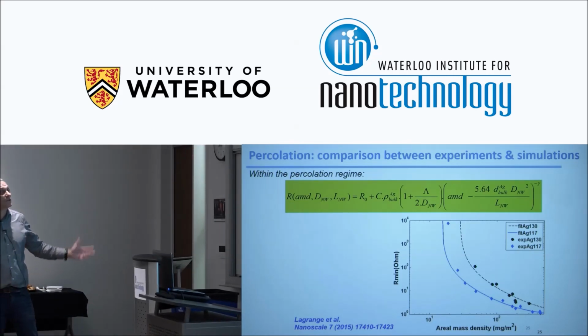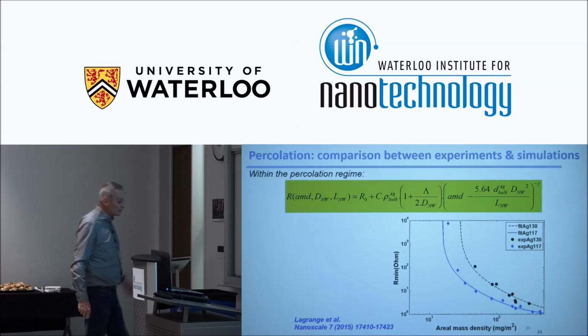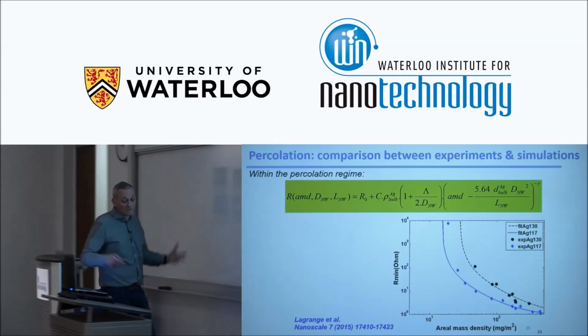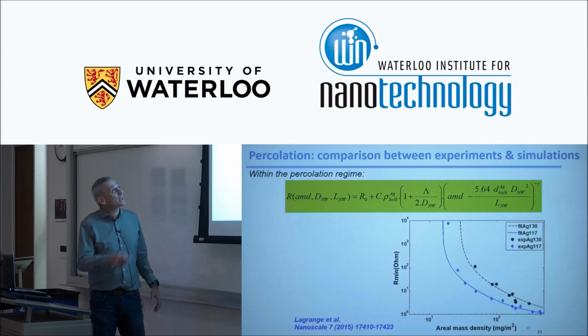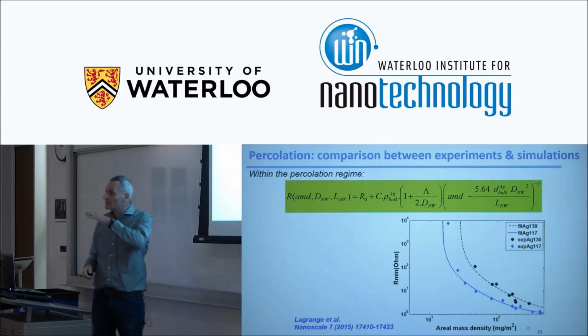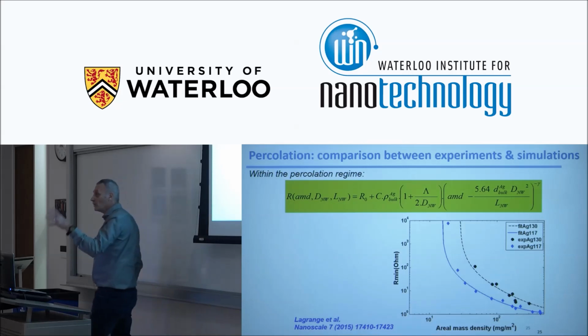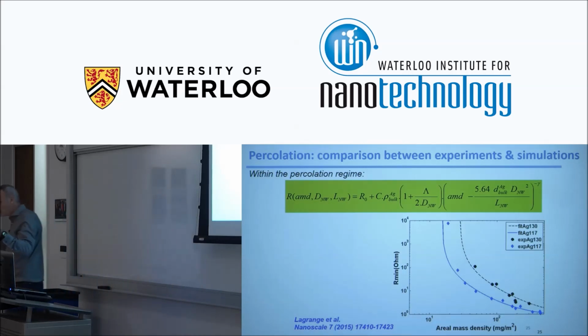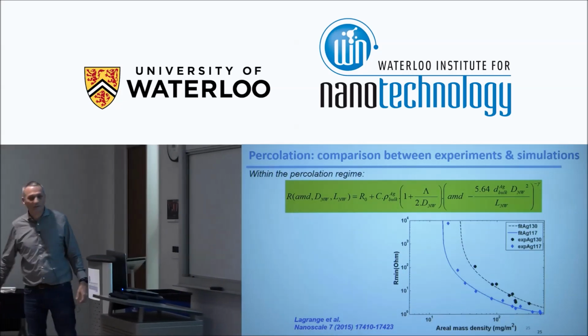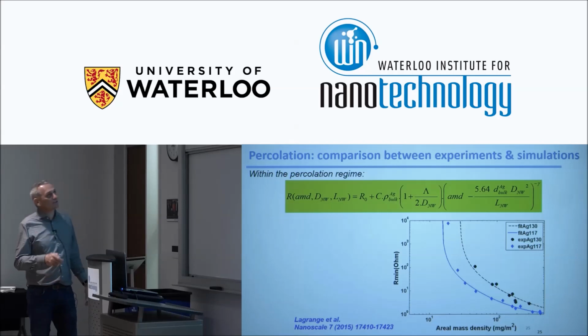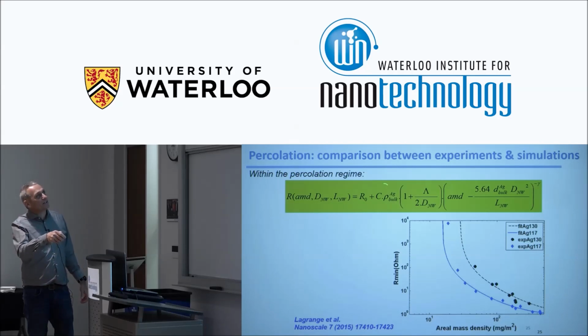So C, I'm not able to calculate it. It depends on the specimen size, for example, and there might be some other parameters. I'm not able to calculate it, so it will be the only fitting parameter, because this one we can measure. If we deposit a thick silver layer, for example, we can say that the resistance is so small that we are going only to measure experimentally the instrumental series resistance. So we know this. C, we don't know, that's the fitting parameter, with the silver bulk resistivity.